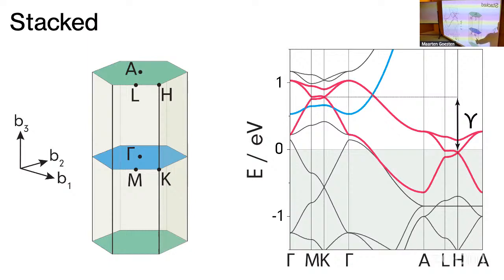So at gamma, the p orbitals are plus minus, plus minus, plus minus, so they are anti-bonding. But when we are moving from gamma to A, which is the crystallographic stacking direction, we are moving from anti-bonding to bonding. So the p orbitals become bonding, and that leads to this large stabilization. What you get in the Kagome lattice when you stack it is a replica of the left-hand part, and I will finish this talk with some considerations of this electronic band, because this is a very interesting electronic state, which is also topologically important.